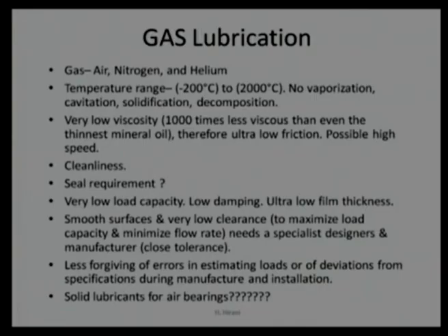Of course, mixing solid lubricant does not mean that you have to mix it in a gas. What we apply is a solid lubricant coating on the surface, a 15 to 20 micron coating, that will give an extra smooth surface. Even if the two surfaces collide or come in contact, they will not wear away easily because of the solid lubricant, since the junction formation will be a low shear strength junction.